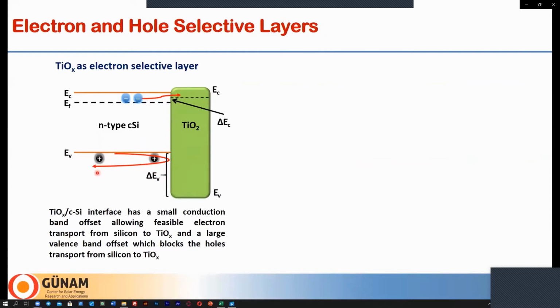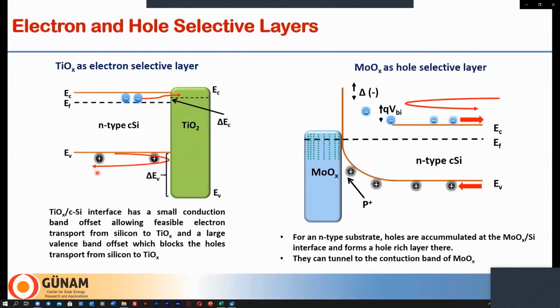away. On the other hand, molybdenum oxide, with its high work function, which can be well above 5.5 electron volt, and in general, when this material, and any material with high work function, is applied to N-type silicon here, accumulation of holes or repulsion of electrons occurs at the interface. The holes in the inversion layer can now tunnel to the conduction band of the molybdenum oxide layer, and electrons are repelled away by the potential barrier formed here.